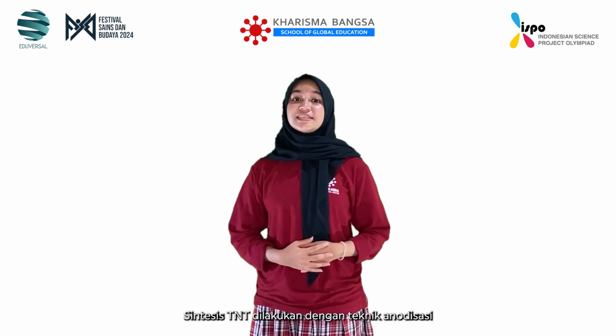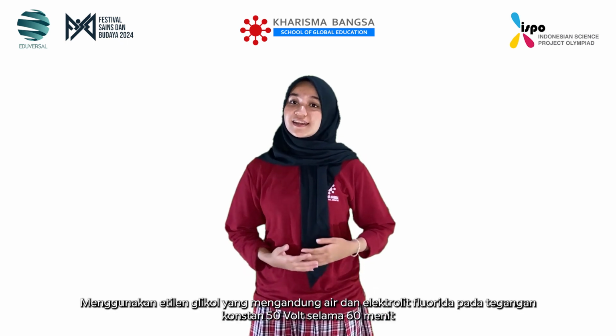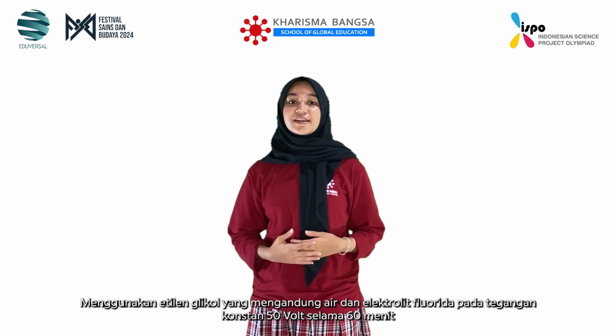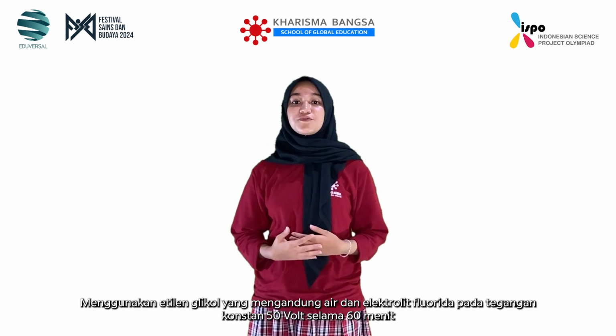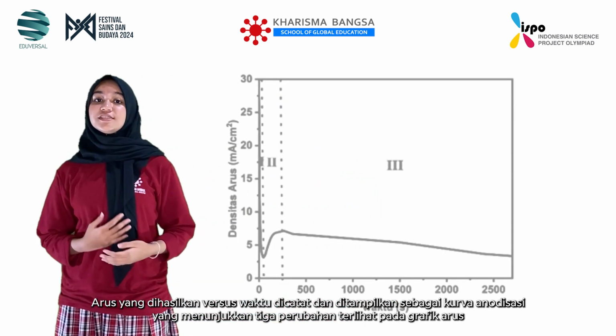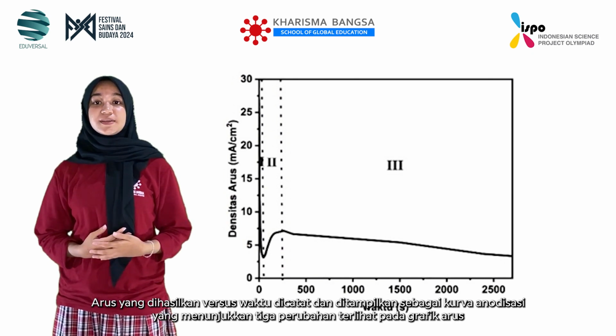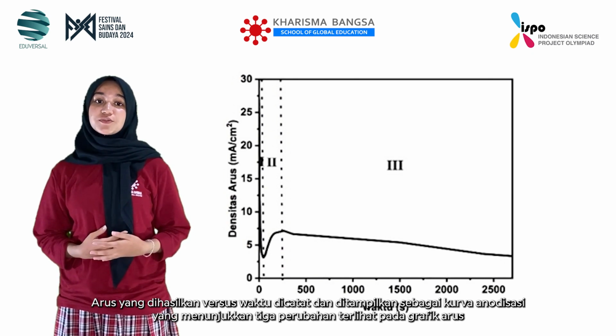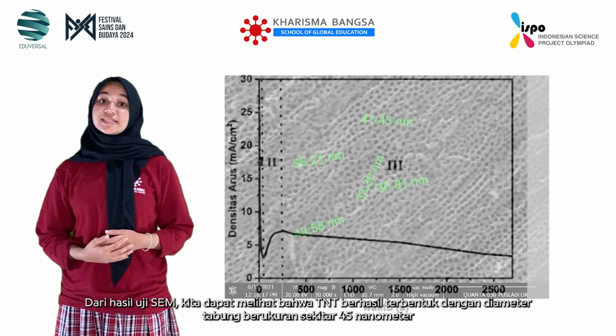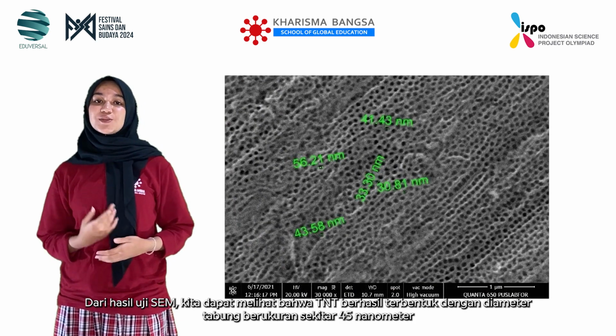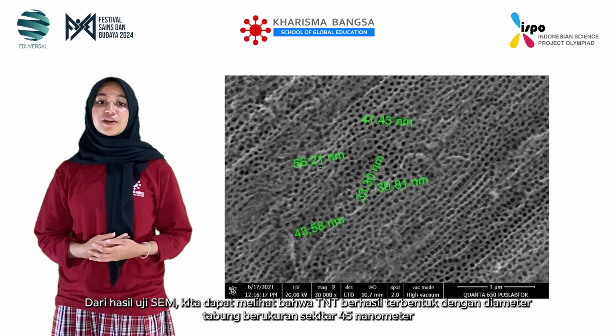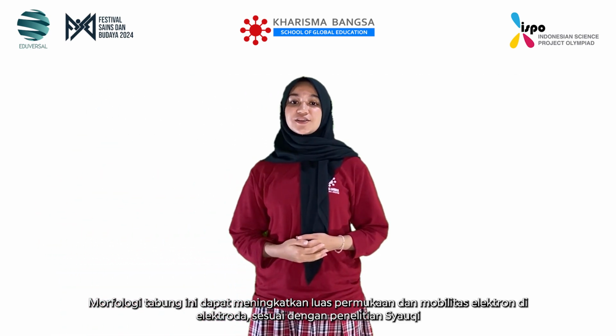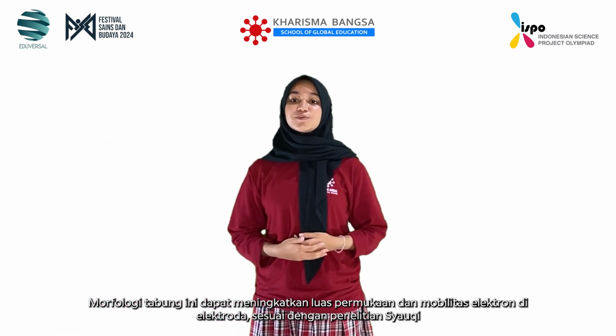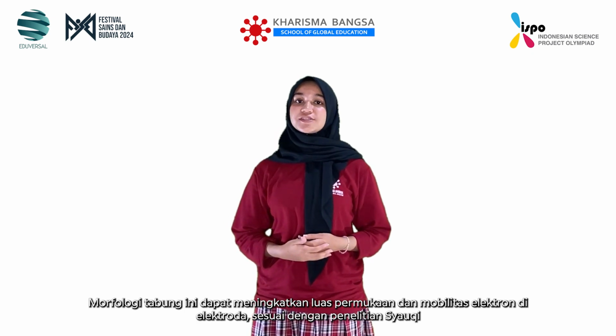The synthesis of TNT was done by anodization technique in ethylene glycol containing water and fluoride electrolyte at 50-volt constant voltage for 60 minutes. The current generated versus time is recorded and displayed as an anodization curve, showing the 3 changes in the current profile. From the SEM top view image, we can see that the nanotubes are successfully formed with about 45 nanometers of inner tube diameter. This tube-like morphology could increase the surface area and electron mobility of the electrode according to Syauqi's report.